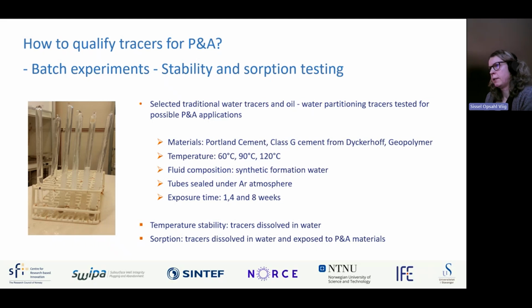We have tested 3 different types of plugging materials, 2 types of cements and 1 geopolymer. And we have exposed our samples to different temperatures from 60 degrees Celsius up to 120 degrees Celsius. Our tracers have been dissolved in synthetic formation water and then exposed to the temperature and the plugging materials for 1, 4, and 8 weeks to look at the stability.